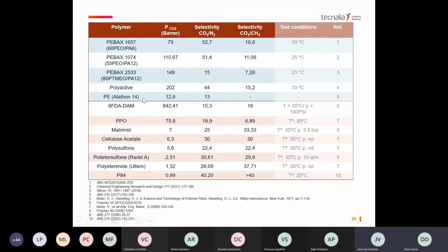supports. Okay, I will finish soon. And on the bottom part, they are all the materials that can be spun directly into monolithic hollow fiber membranes. So I will give an example with P84. It has a low permeability of carbon dioxide, but the selectivity is good. So if we manage to make a very thin top layer, the permeance will be higher. And then I will speak about 6FDA-DAM, which is very permeable, but the selectivity is lower, so we try to increase the selectivity. And then I will show a bit how we change the chemistry in PEBAX type polymers.